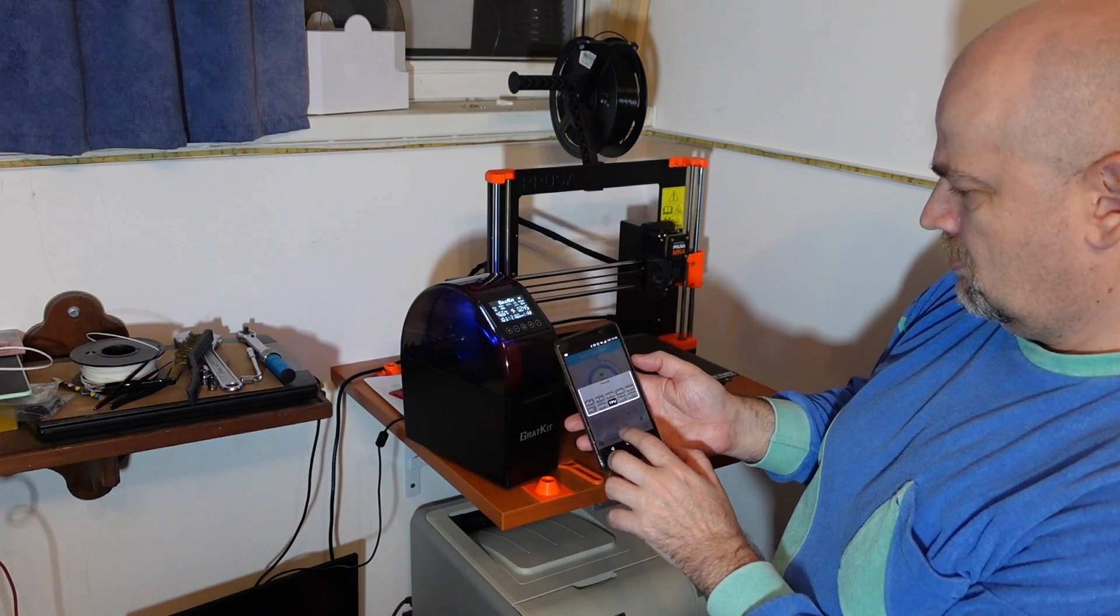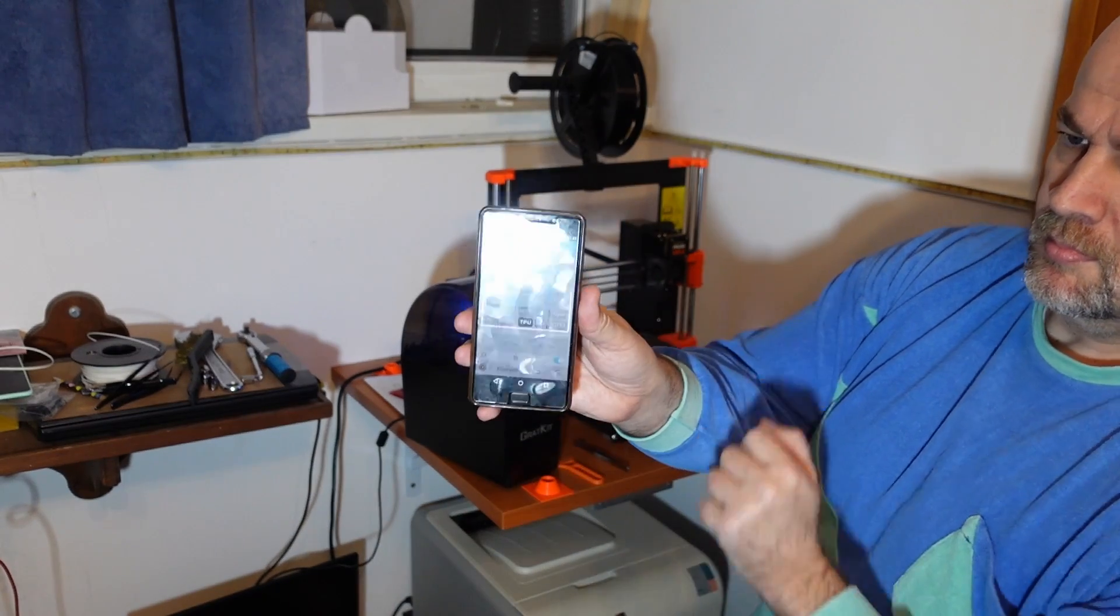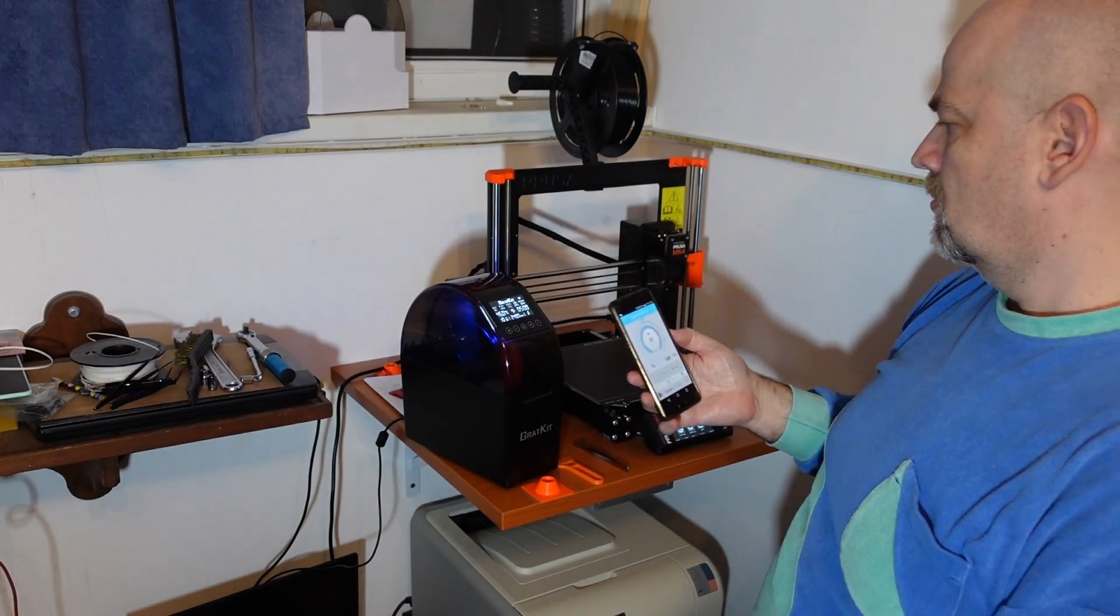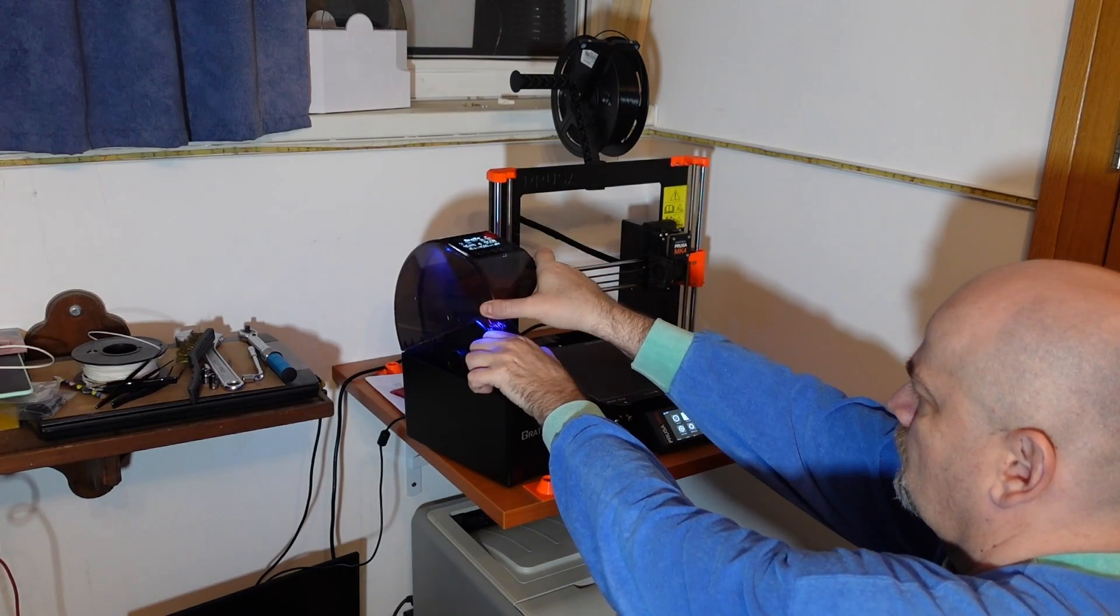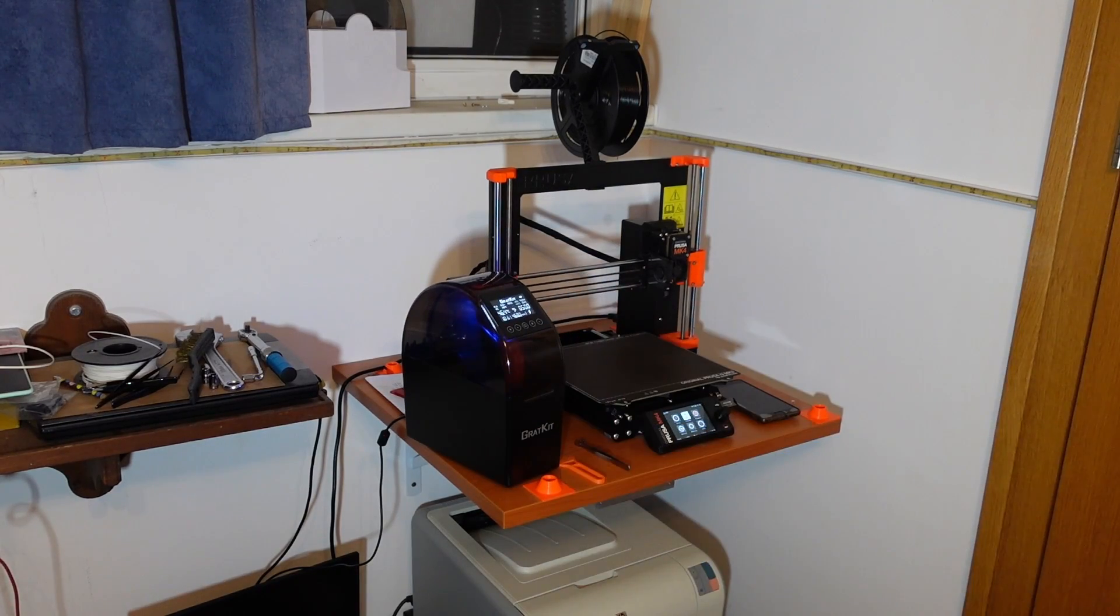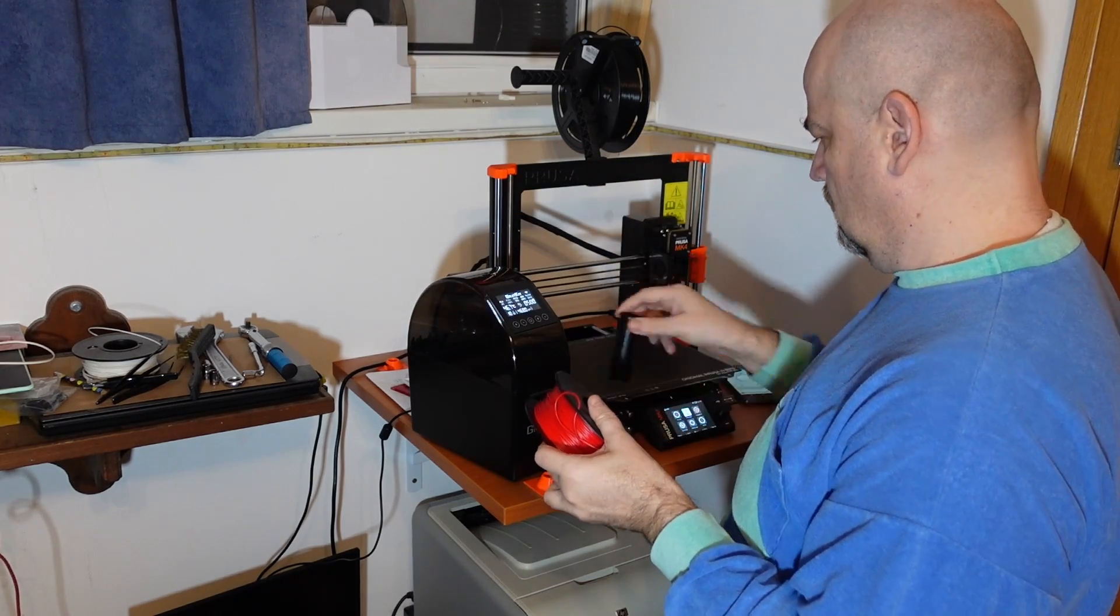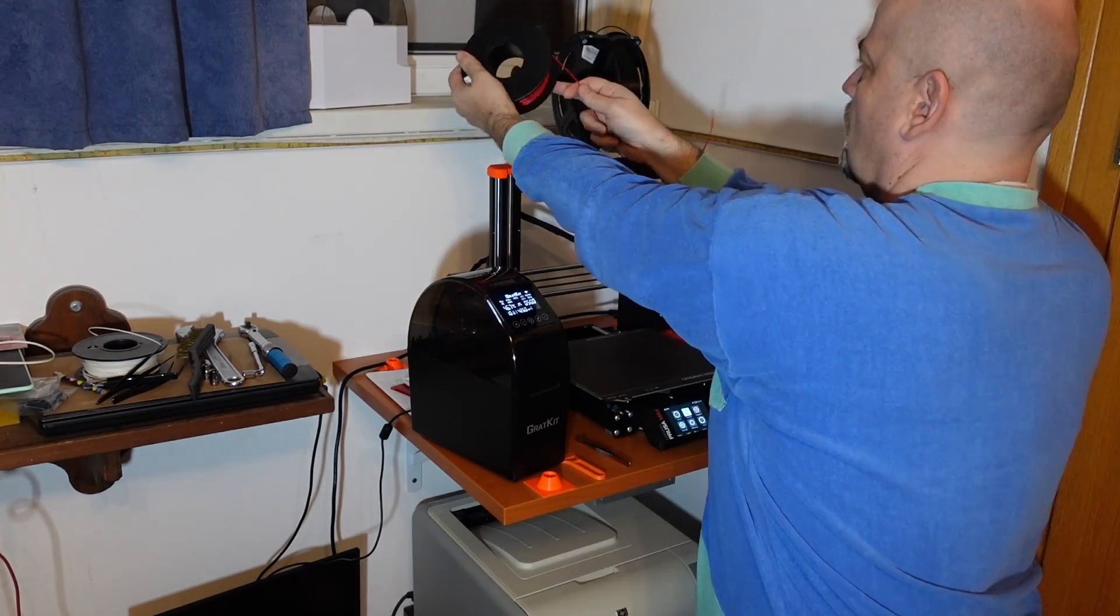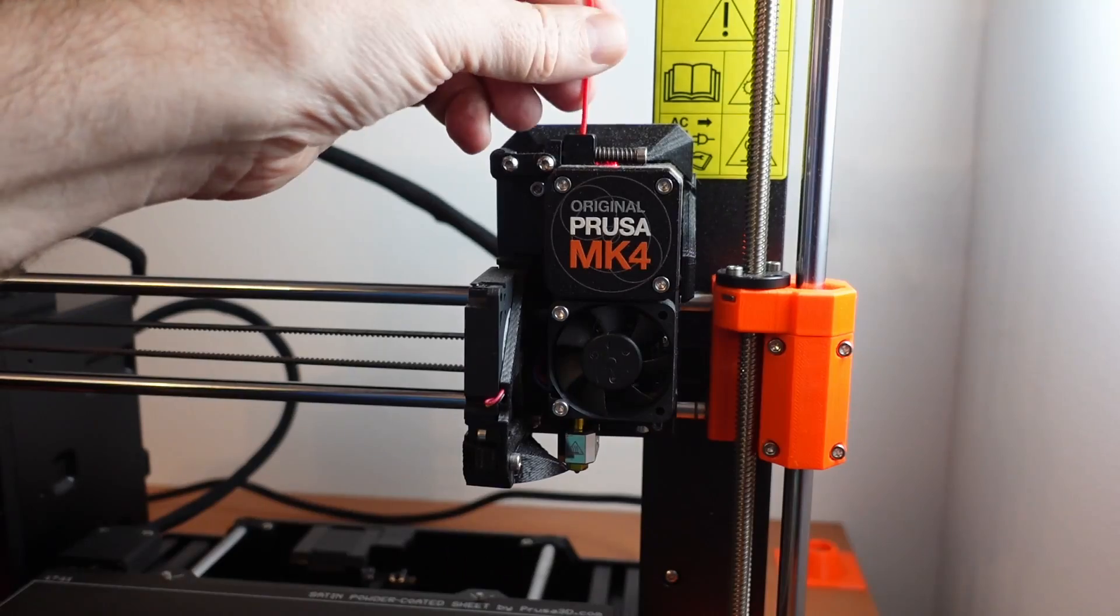It uses the application so I am using the preset values for TPU filament. It was 55 degrees Celsius for 4 hours or something like that. Only every hour I rotate the spool a little bit to have more equal drying. And the printing will be from the open air, the only reason for this is that I don't have a solution for nice exit from this filament dryer.